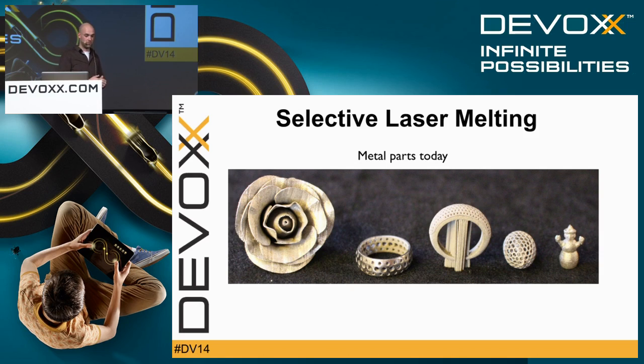This is a photo of some of our demo parts at KU Leuven. Now I want to point your attention to the third part. That's actually a ring with support material. If you are going to build a part in loose powder without any solid material touching it, you will have a bad quality part. The heat you inject will stay trapped in the powder and you will get dross formation and the whole piece is just bad. So what we do is we build support material starting from the base plate up and then really attached to the part that you're going to build. In that way you have a good thermal conductivity and the part is being held together.